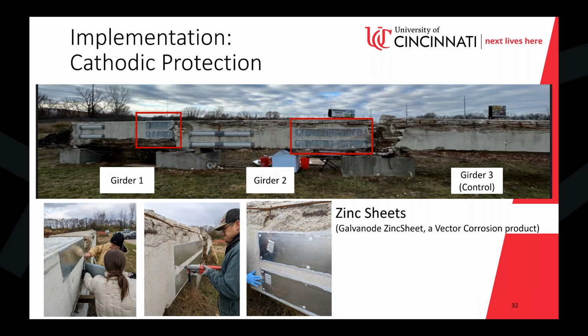It really is just a process of, you can see in the far left bottom, effectively just pasting it on and then sealing up the edges, because critically you don't want water sitting under here and delaminating it. Especially, we have this vertically mounted, but this would be on the underside of the girder in an actual application. But you apply the epoxy, you put the metal wire leads on it, and that's the installation process. It was fairly quick and easy. You can see a couple small drill holes where we mechanically mounted it as well, but not going very deep at all into the surface there.